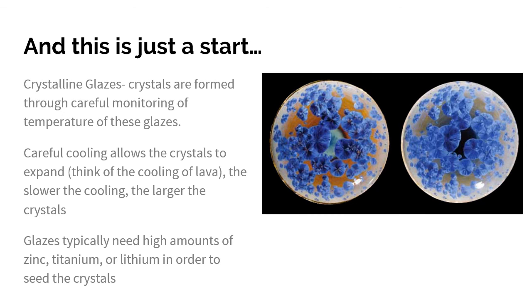If you think of the cooling of lava, obsidian cools very quickly, so there's no time for a crystal to form. Whereas granite is also cooled lava, but it's cooled much more slowly and you get that crystal formation. So it's a similar concept here, that a crystalline fired kiln is put at its high temperature to melt everything, and these seed crystals start to form, and then it's cooled down and kept at this special cooling temperature to encourage crystal growth, and then it's cooled fully and the piece can come out of the kiln. So crystalline glazes usually have a slightly different chemical composition with a lot of zinc, titanium, or lithium to be those crystal seeds. But it's a really popular technique. It's really beautiful. There's so many options.